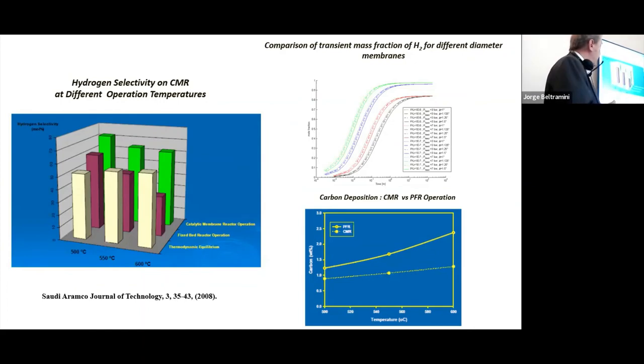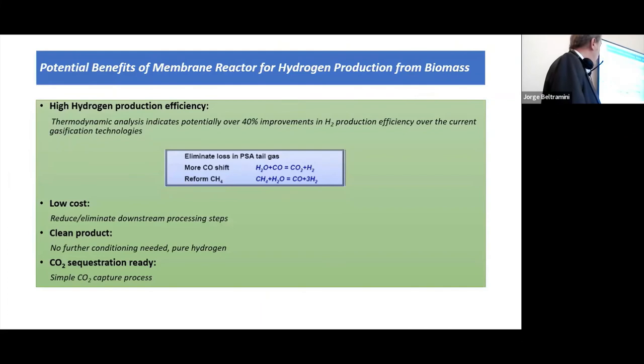We studied the conditions of the mass hydrogen at different states of the membrane, and we see here the great separation of hydrogen through the membrane. So it's possible to do with biomass. We are now trying to experiment with biomass, a very heavy fraction of biomass, to produce a fuel oil that can be from a particular sludge, or a very high fraction of a bio oil, which can be converted using this approach into hydrogen.